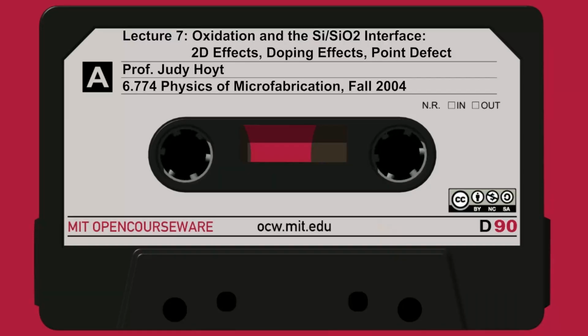If you're making a device and you implant a region for a source drain, and then you go to oxidize it, it's going to have a different oxidation rate compared to those parts of the chip that are being oxidized that don't have high doping in them. So in SUPREM, you can easily take that into account.